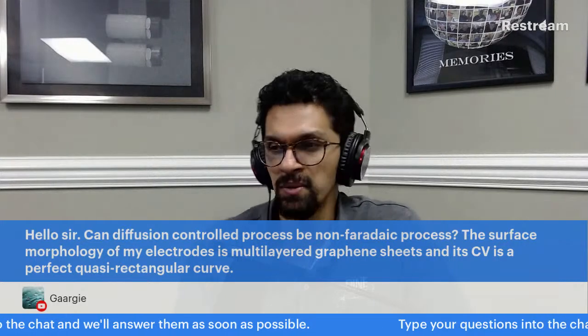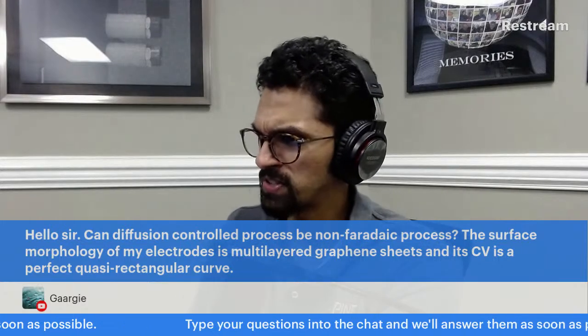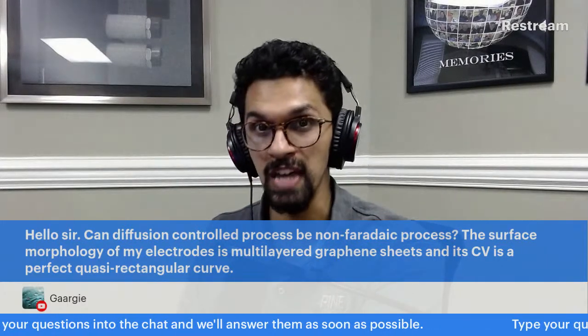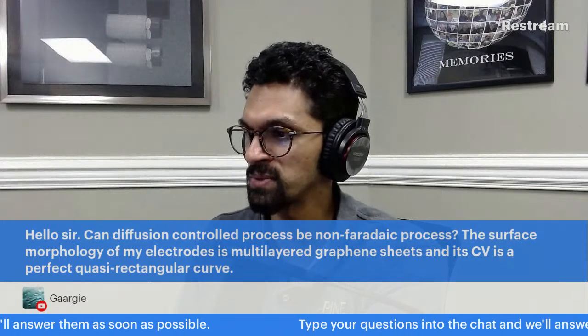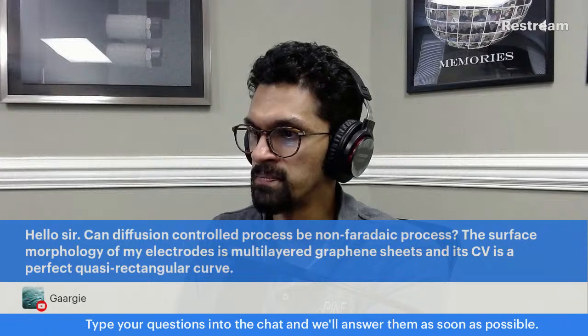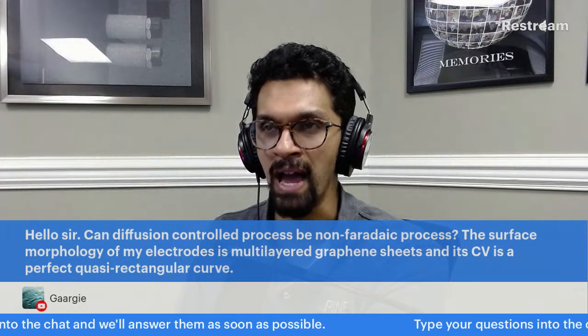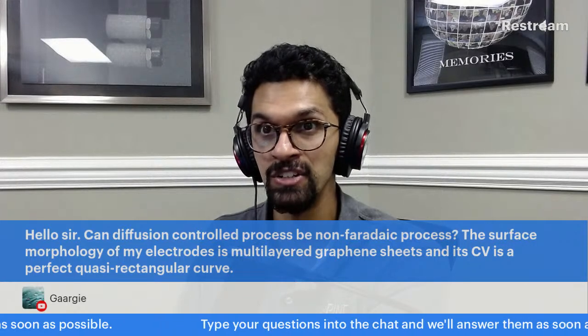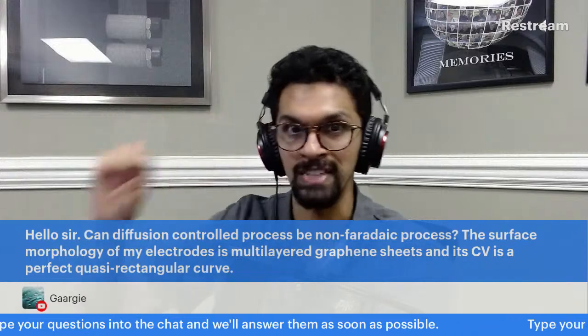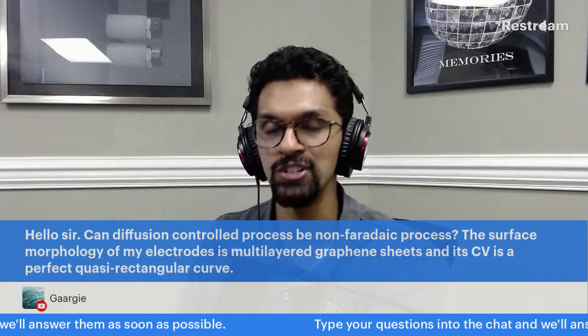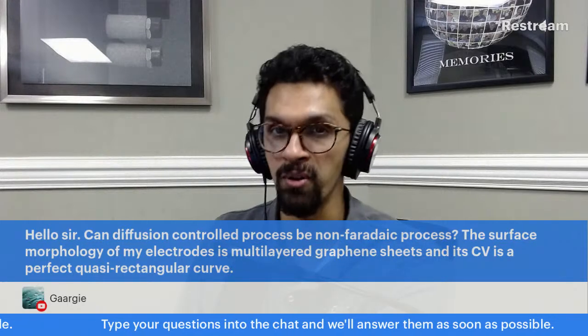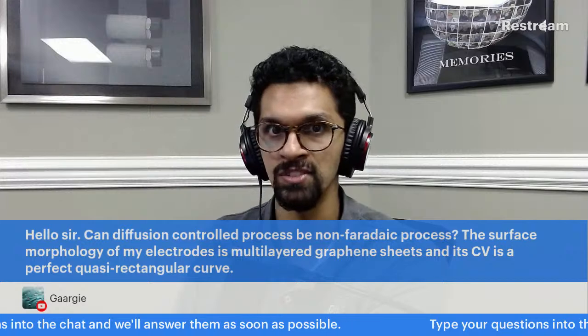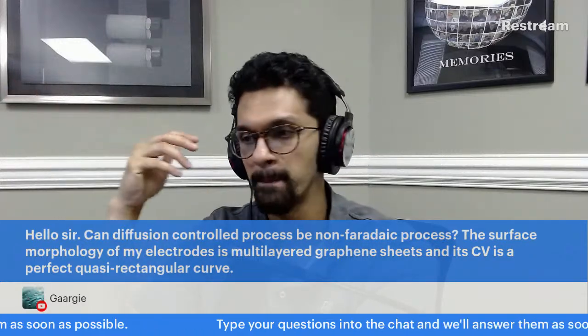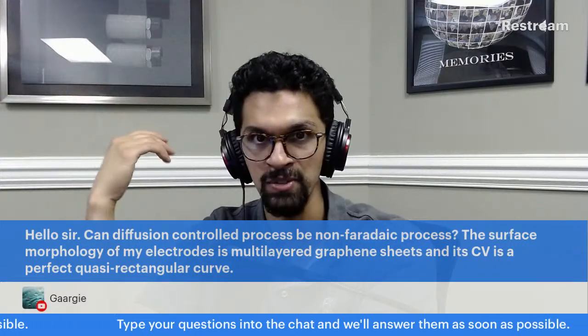You can do a scan rate study of this. So Gargi, one thing that you can do is a scan rate study. I'm curious about what the scan rate study is. If it's a capacitor, the capacitance should have a linear relationship. So the current response that you get for a quasi-perfect rectangle, that increase in current should be directly proportional to the scan rate of your system, because the current is equal to the capacitance times the scan rate. I would be interested in seeing whether or not you have a linear dependence on the current for your CV with this quasi-reversible thing.